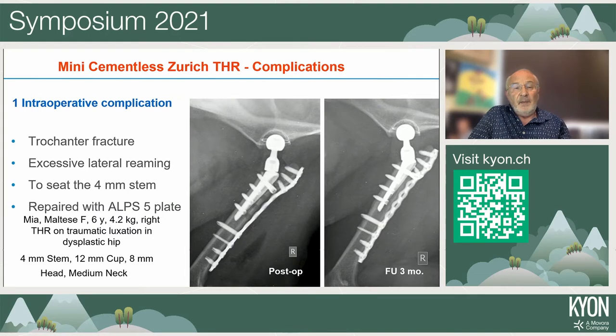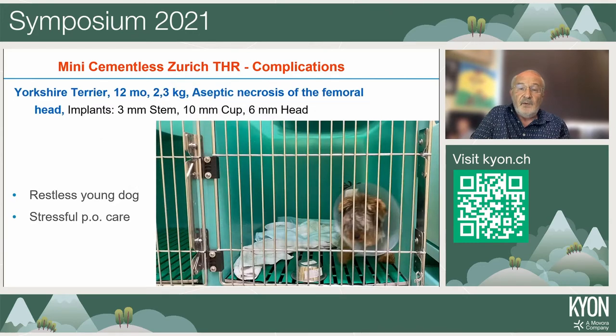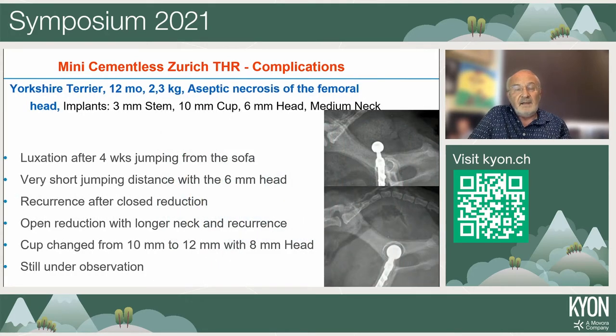We also had one intraoperative complication, a trochanteric fracture, because of excessive lateral reaming, and that was because we went to a too big stem. Why? Because the 3 millimeter stem was too small and the 4 was a little too big. We wanted to put that bigger stem, but of course we weakened the trochanter, and then we caused the fracture during the reaming and the reduction. But that was fixed with a plate, and you can see that at 3 months everything is okay. I want to go back to my small Yorkie, just to tell you that this experience taught us that it's better to have a cup that is 12 millimeter that can hold an 8 millimeter head.